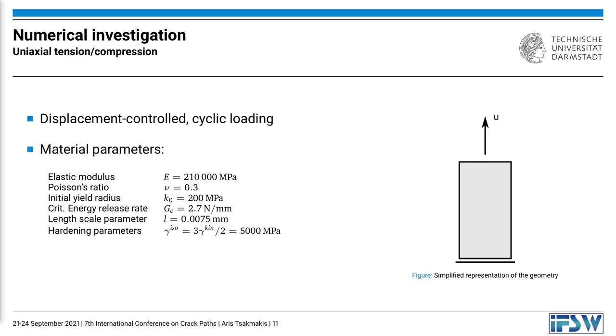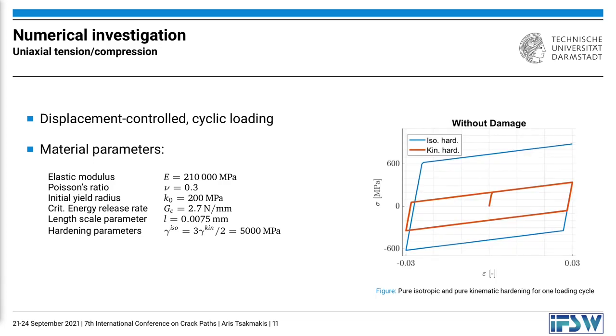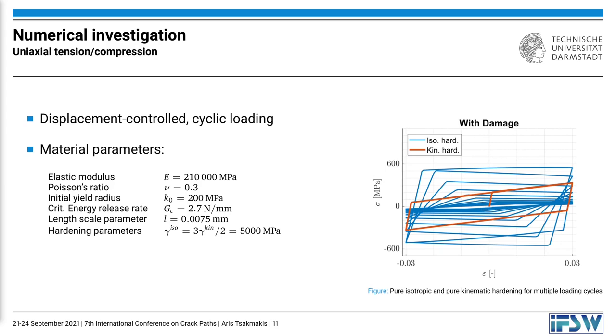The first example discussed is that of uniaxial tension and compression. On the right side we see a simplified version of the geometry, and displacement controlled cyclic loading conditions are applied. The material parameters are shown on the left, and in particular the hardening parameters for isotropic and kinematic hardening are chosen so that the monotonic uniaxial stress-strain curves are identical for both types of hardening. On the right side, the stress-strain curves for both types of hardening are shown with no damage included and for one loading cycle. During the first loading branch both types have identical stress-strain curves; when unloading and reloading, kinematic hardening produces a closed hysteresis loop whereas isotropic hardening produces a widening curve.